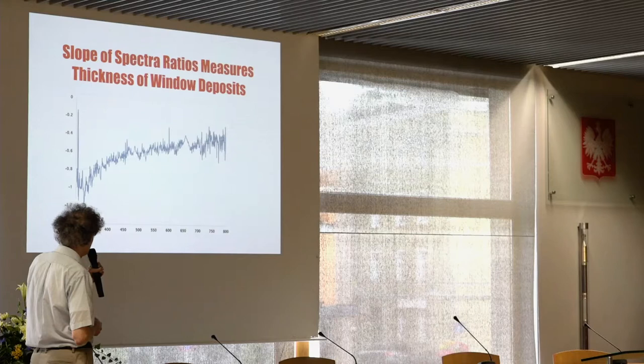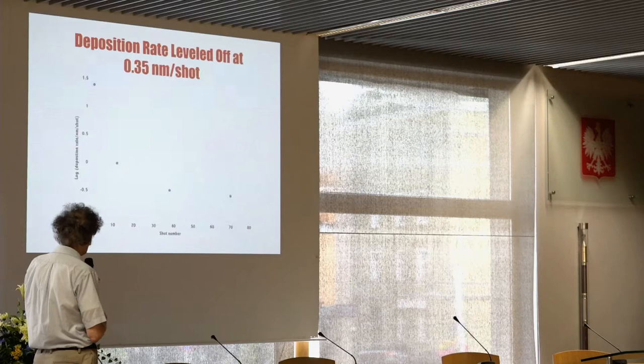Comparing a very recent shot to a shot from about a month earlier, in addition to the overall spectral slope from absorption, the hydrogen lines appear stronger and the beryllium lines — visible as negative dips — have gone down by about a factor of three over the course of the month. So erosion appears to be slowing.